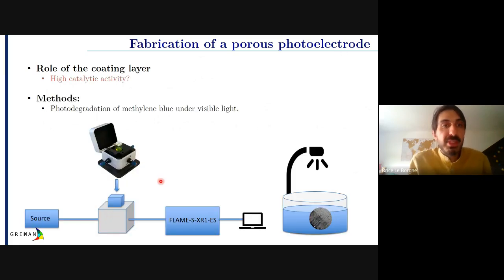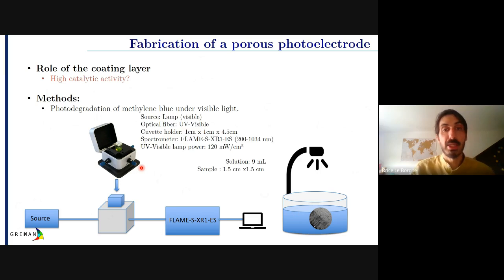So the first thing is indeed, what about the catalytic activity? We are not a lab specialist in photocatalysis. That's why we're working now with the people in Catania. But anyway, there is a quick test to perform that, which is to use methylene blue degradation. So basically, you put your sample within a methylene blue solution, and with a catalyst, you can degrade methylene blue faster if the catalysis is efficient. And then, by measuring the absorbance spectra, you can calculate the concentration of methylene blue and know the degradation rate. So that's what we've done.